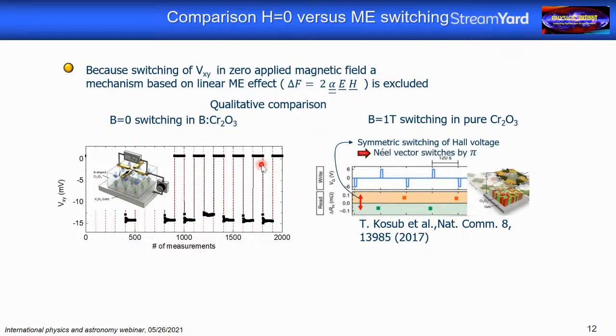Now, in our case, the situation is different. No magnetic field is applied. We do not switch between symmetric voltage or resistance states. We switch between almost zero and a non-zero state. And compatible with the fact that no magnetic field is applied, we think that our switching must be a 90-degree rather than a 180-degree rotation switching. And that then makes it also compatible with symmetry arguments.